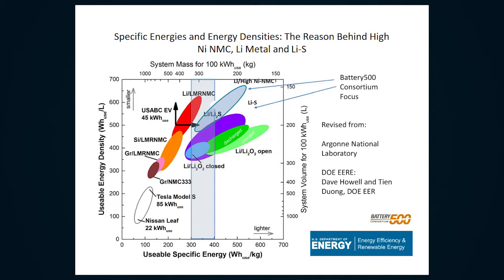Another system that can be very inexpensive, of course, is lithium sulfur, because sulfur is really cheap and has a very respectable theoretical specific energy. And people from the audience ask about recycling lithium metal. At this time, recycling lithium metal may not be so economic, but if you use high nickel NMC, recycling cobalt and nickel may be more important at this time because it's pretty expensive and it's used in larger quantity.